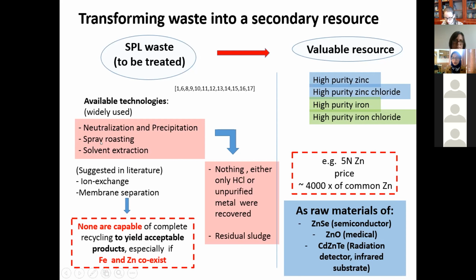Then we have spray roasting, and there are two methods of spray roasting. In one, we use waste heat from another plant, at 450 degrees Celsius, to regenerate the hydrochloric acid. This is good, as we can fully recover all the hydrochloric acid, but not the metals. Then there is also the fluidized bed spray roasting type, but it consumes more energy because it needs 650 degrees Celsius.